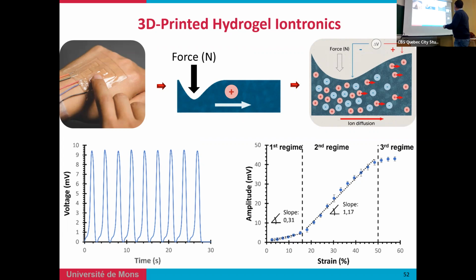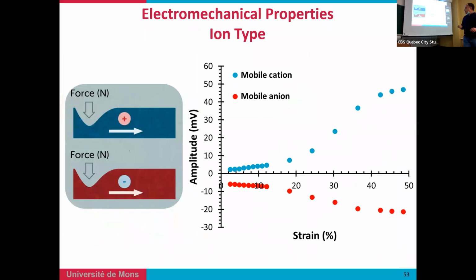Of course, when you investigate this, you need to control the mobility, so you have different regimes that are very important. But the second regime, which you obtain after a certain deformation, gives a linear relationship. So therefore you can have a certain monitoring of the touch force against the amplitude that you record at the end.